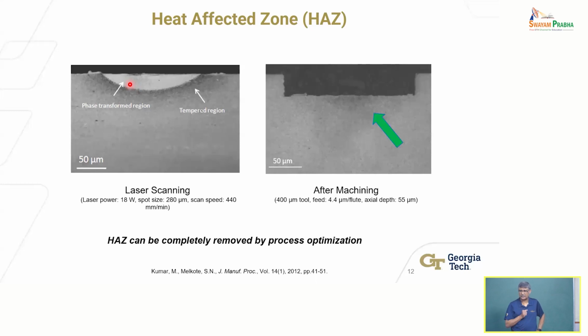It's phase transformed. It's actually martensitic. Okay, if you all remember your iron carbide phase diagram, right? So with very rapid heating and very rapid cooling, you're going to actually produce martensite, right? After austenitization, and you will actually cause a very hard phase to form. So here you're doing this by controlling it in situ, right? So the material the tool sees is softer, but nevertheless, you can see that there is some darker region here. Okay, that's typically how a heat affected zone looks like. It's not too bad. Okay, if you look at welding, in welding, you'll see a heat affected zone as well, right? So this is evidence that there is some softening, which is why I'm making the point that you have to control the energy to soften most of the material that you're going to remove to enable easy machining, but not do any damage beyond that, okay?